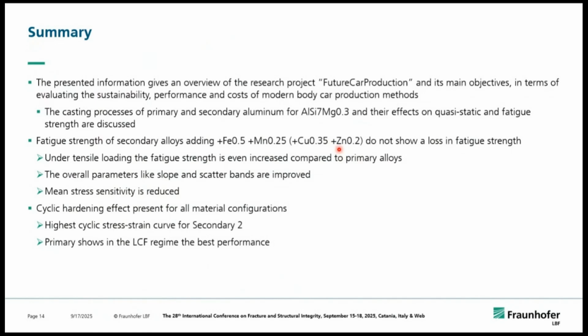What was for us somehow surprising, and a benefit in performance, I would say, is that we don't need to be afraid of recycled alloys, even when we have higher fractions of iron and copper. So the results prove for us, with a rule of thumb, that we have comparable fatigue results for something like the primary alloy and the additional ingredients that we have here with copper, zinc, and so on. I would rather say that we have a bit of an improvement of the data. You saw that the slope for the secondary 1 improved a little bit, got a bit flatter. We have comparably low scatter bands, and the mean stress sensitivity is also reduced while adding those iron and manganese fractions.